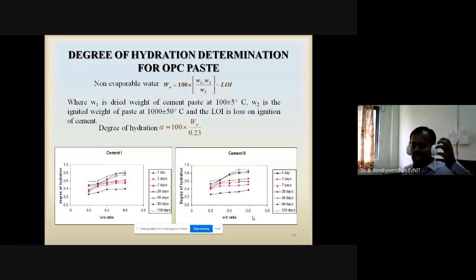That's how we can determine the degree of hydration: WN divided by 0.23. So we determined the degree of hydration for various water cement ratios and various curing ages, and also plotted it for cement 1 and cement 2. The figures look like this. Obviously, cement 1 is the coarser cement and cement 2 is the finer cement. So cement 2 has more degree of hydration and cement 1 has less, and over the period of time it is increasing, because more and more CSH gel is forming.